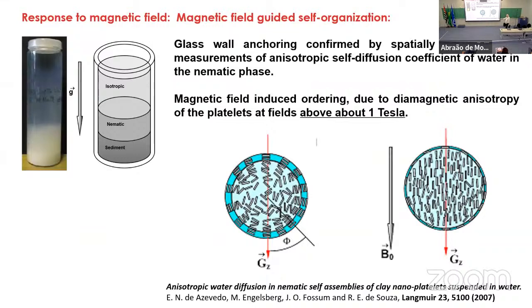This is another example of something we have done in this area. This was done with people in Recife, actually, in Pernambuco. And we studied the nematic phases in MRI. So we studied anisotropy in water diffusion. Water diffuses along the platelets, but not perpendicular to them. So then we can actually characterize the nematic phase in the magnetic field in this way.